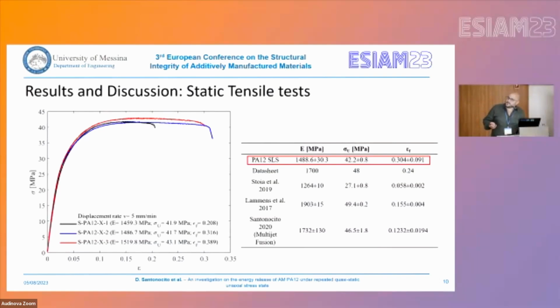Here I report the value of the Young modulus, the ultimate tensile strength, and the deformation at failure of the specimen. And here I also report some other values from the datasheet of the material and other literature research present. The data is quite in agreement with the literature.